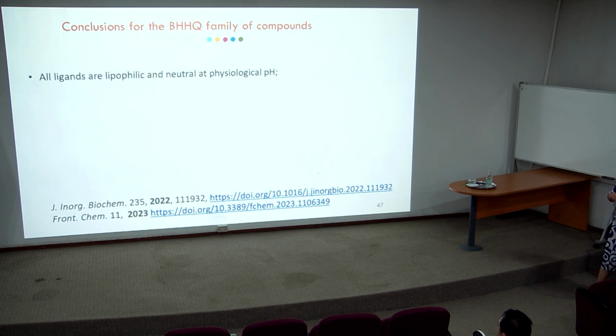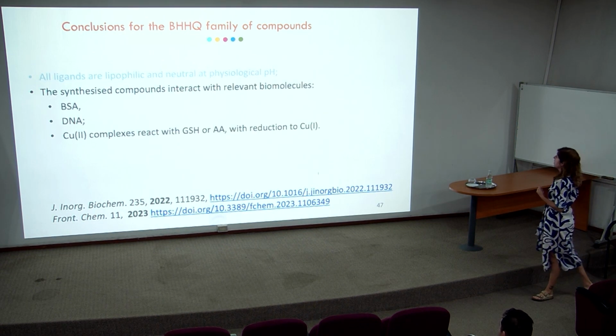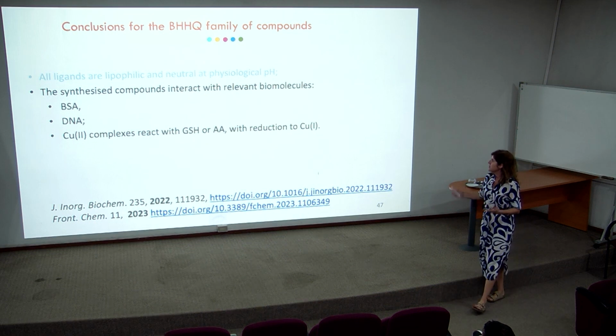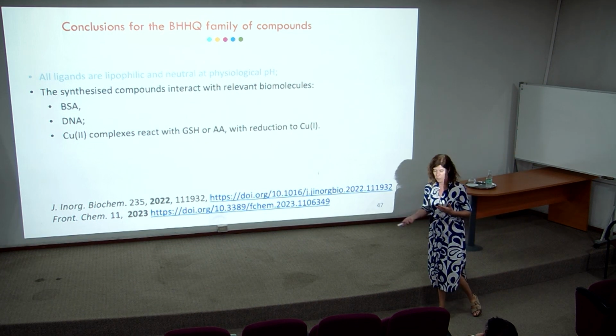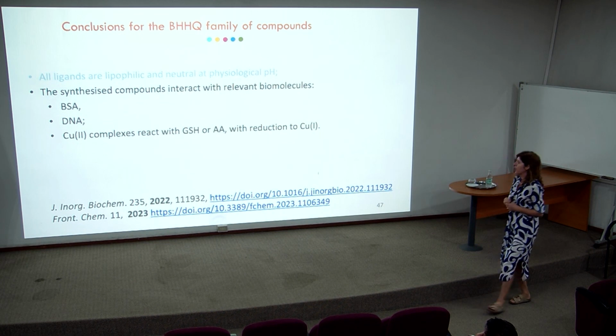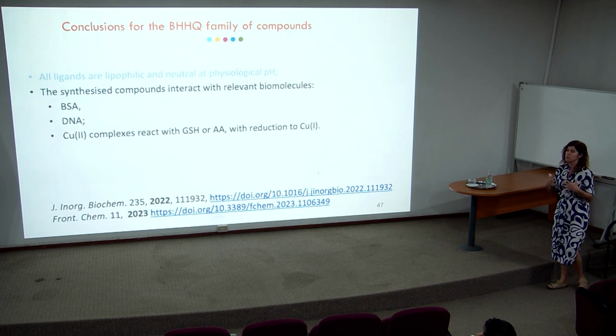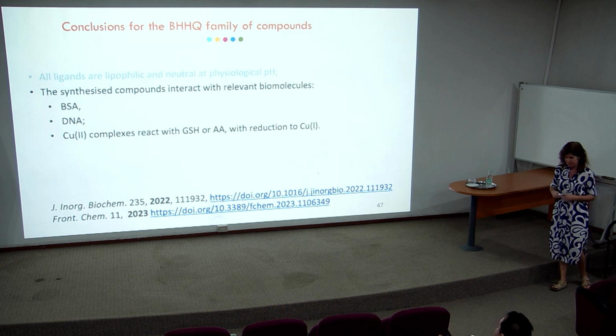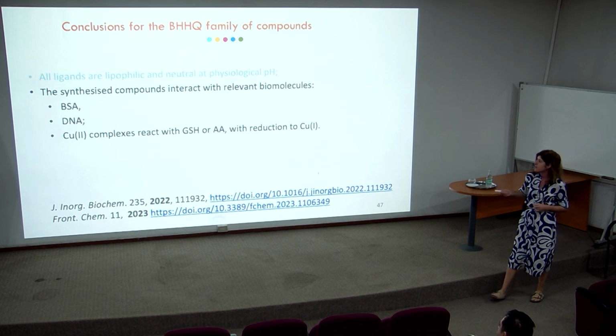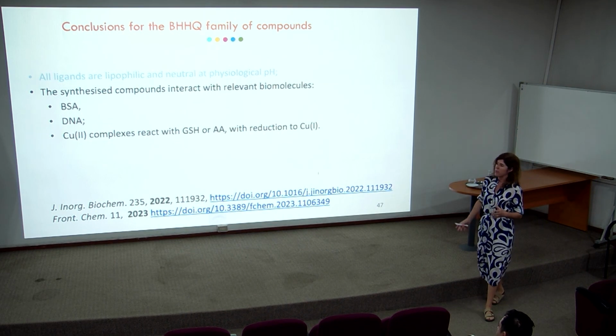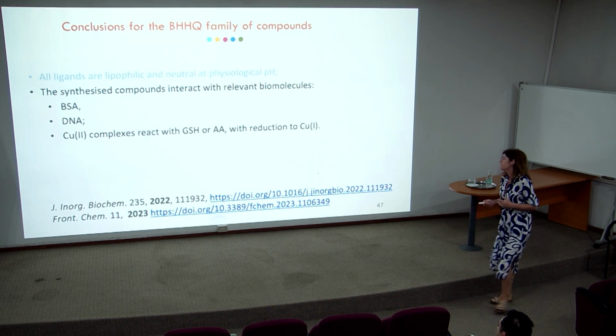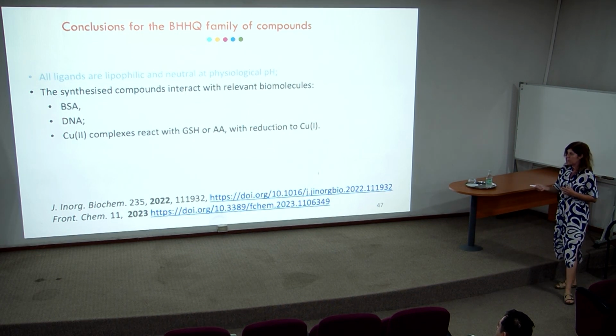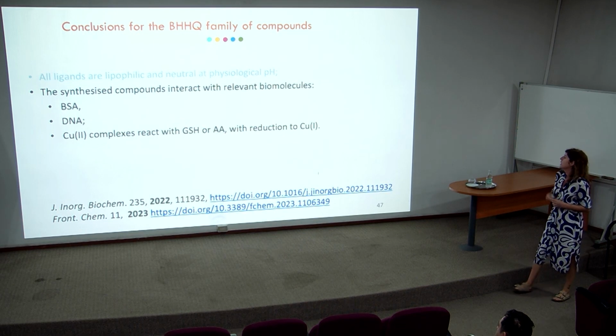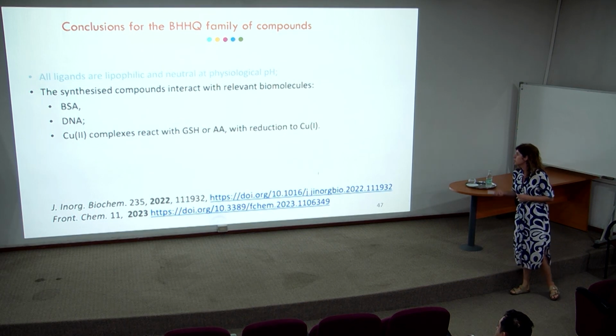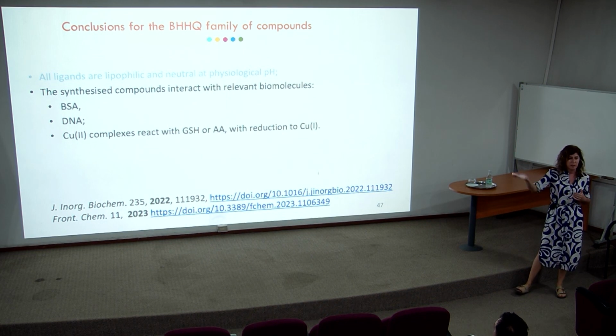So again, these ligands are still quite lipophilic. They are neutral at physiological pH. The metal complexes interact with relevant biomolecules, so they can be transported by albumin, which can also solubilize them in the cell media of these cytotoxicity studies. They interact with DNA, although not by intercalation, and the copper complexes are able to react with glutathione or ascorbic acid with reduction to copper 1 and the release of the free ligand.